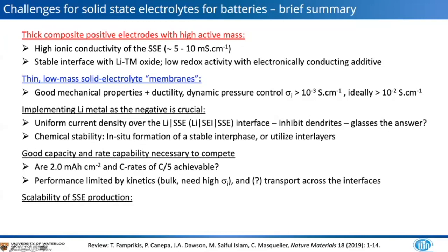The electrolyte itself, the membrane, needs to have good mechanical properties, and that means that ideally it is a relatively ductile material that will enable dynamic pressure control to be established, and again, these criteria for conductivity. So I won't get into these factors very much. I've already explained that using lithium metal as a negative is fairly crucial to really establish commercialization and a competitive edge for these batteries.